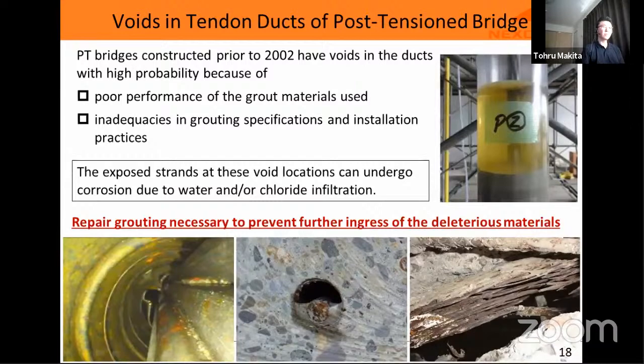Management of post-tension concrete bridges is one of the biggest challenges in NEXCO Central's expressway operation. Among several maintenance activities that need to be done for management of post-tension concrete bridges, today I will talk about repair grouting. It is said that post-tension concrete bridges constructed prior to 2002 in Japan have voids in the ducts with high probability because the grout material used had poor performance, such as large bleeding. And specification and installation practices of grouting were inadequate. In order to prevent further ingress of deleterious materials such as chloride, repair grouting is quite important.